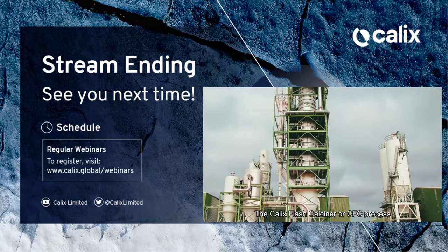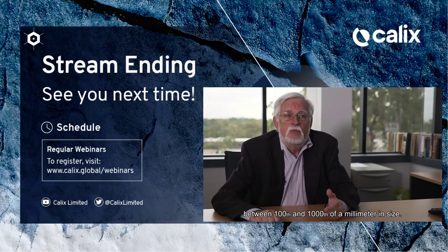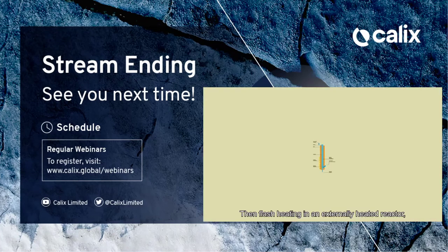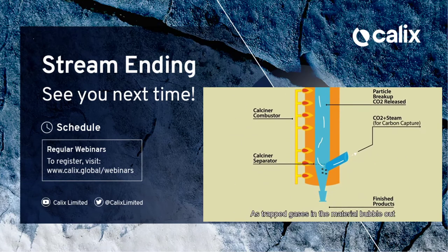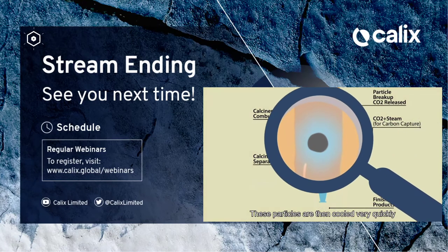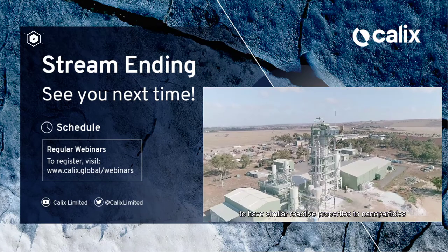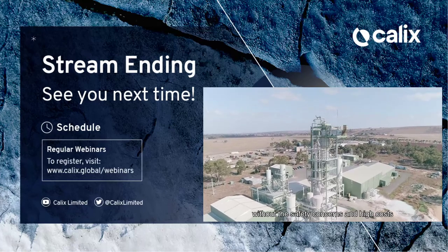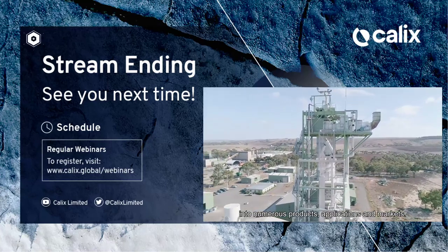The Calix Flash Calciner, or CFC, process involves grinding minerals or other feedstocks to between 100th and 1,000th of a millimetre in size, then flash heating them in an externally heated reactor in a very short time, up to about 950 degrees centigrade. As trapped gases in the material bubble out through the particles, they create highly porous structures. These particles are then cooled very quickly, leaving a very porous, honeycomb-like structure. New materials produced by the CFC are proven to have similar reactive properties to nanoparticles without the safety concerns and high costs, but with all the benefits that nanotechnology is developing into numerous products, applications, and markets.